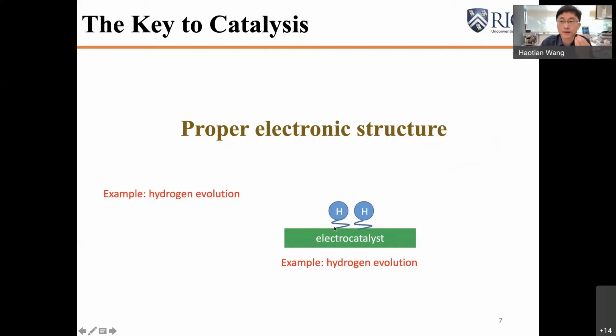The strength of the chemical bond is determined by the surface property of the catalyst. And you can think about that. If we bind the intermediates too strongly, the product release process will become very slow. But if we bind the intermediates very weakly, then the electron transfer process will become slow. So basically, in principle, our idea is to design an electrocatalyst that has a proper electronic structure that can bind your reaction intermediates, like protons here, just properly, not too strong, not too weak, so that you can deliver the maximum catalytic performance.